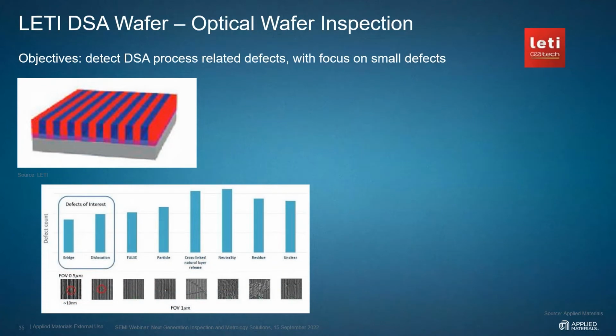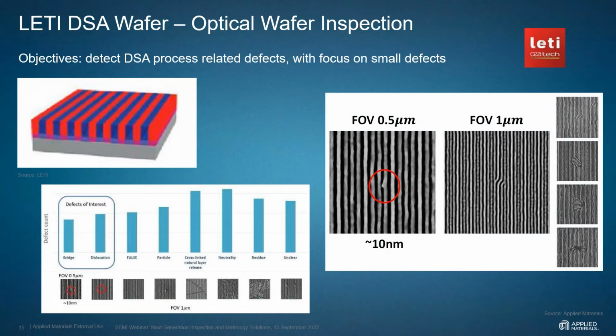We also demonstrated our detection on a Leti DSA wafer. So here we received a directed self-assembly wafer, and the objective was to detect DSA process-related defects with focus on small defects. So the bottom left shows a nice Pareto of multiple types of defects with focus on bridge and dislocations. And on the right-hand side, we can see some of the beautiful small defects we found of dislocations and the champion defect of the order of 10 nanometers, which is quite significant, with very good feedback which we received from Leti versus the baseline that they use.